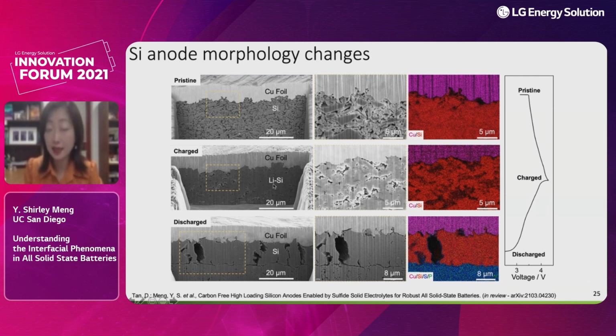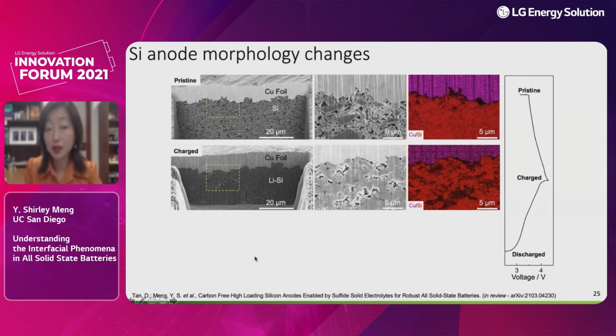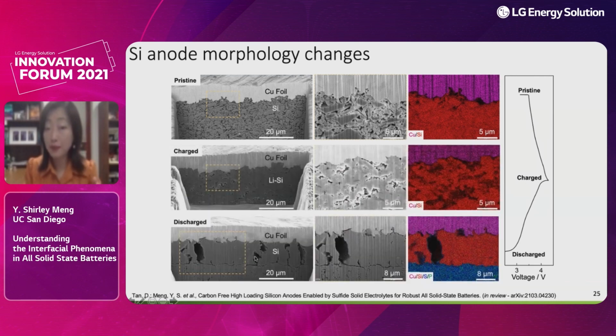Because the lithiated silicon is actually very, very soft, under the stack pressure of 20 to 30 megapascal, the microstructure of the silicon lithium completely changed. When you take lithium out of the silicon, it never goes back to the original shape. This process happens in one step, and it's a complete transformation - you can consider it like a formation cycle for the solid state batteries.